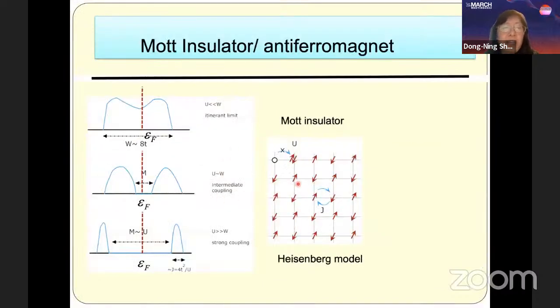The antiferromagnetic order at half filling can be easily understood based on Mott insulating physics at large U. With increasing Hubbard U, the energy band splits into a lower Hubbard band and an upper Hubbard band. In the lower Hubbard band, each site is occupied by one electron, and there is a Heisenberg exchange interaction between nearest neighboring electrons, so they tend to form antiferromagnetic order.